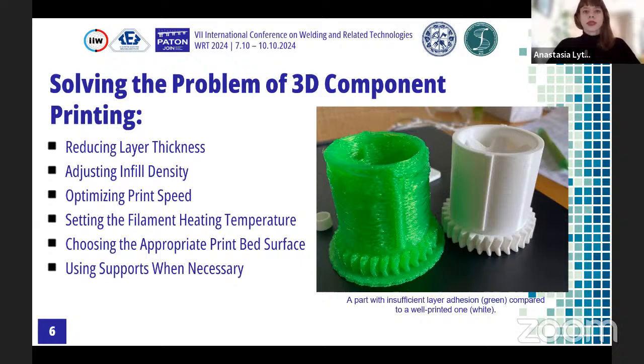Inappropriate parameters can result in a part exhibiting poor surface quality, with deformed filament layers that have weak adhesion to each other, causing a curling defect or other defects. And high layer thickness and infill density cause the material to become more prone to deformation due to increased internal stresses during cooling.